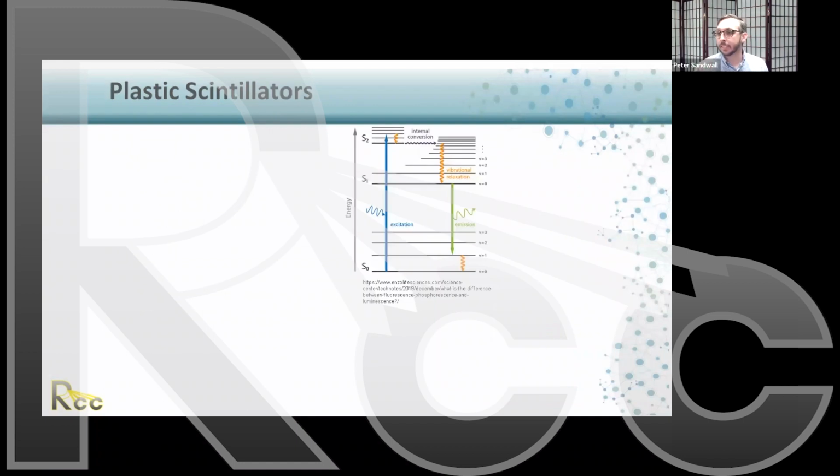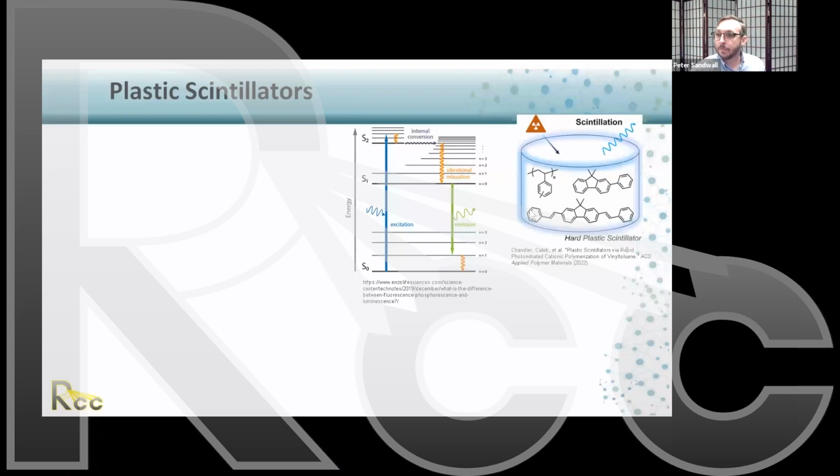So they operate through luminescence or through fluorescence. And I can actually talk all about this one slide, so I'm going to do my best to go quickly. You get light that comes in, it excites a molecule, and then there's some internal conversion, a little vibrational relaxation, and then emission of a different color light. The way this works in scintillators is they've got a whole family of compounds built into this plastic, which downshift the radiation from high energy to lower and lower energy until it comes out as light.